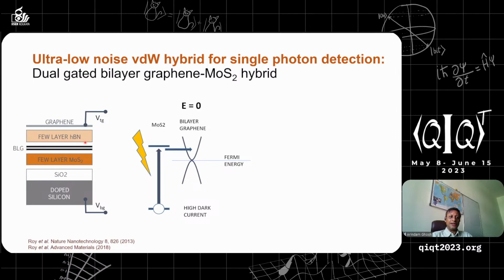In order to do that, what we did some time ago, we created a structure where graphene is sitting next to a transition metal dichalcogenide. I told you about graphene, which conducts electricity very well because it has high mobility. But in the case of transition metal dichalcogenide, which is a material that has a band gap, you can use it to absorb light. So that's a wonderful property to have. And if you put them together, molybdenum disulfide is the absorber region, like the absorber region in your avalanche photodiodes as well. But then the absorber region gives the electron to the graphene region to electrically conduct the current.